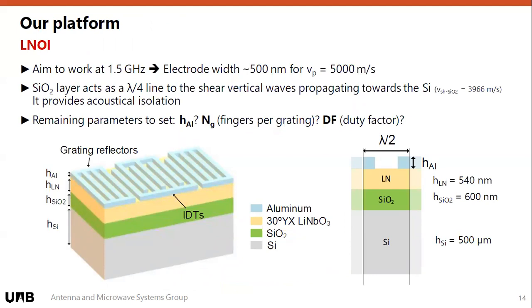So this is our platform and what we have been developing. Initially, we started working at this. Our aim was to work at 1.5 gigahertz just to have something that was manageable, that was lithographically not at the extreme of anything, so that we could focus on the mechanical properties of this. So if we assume, for example, a phase velocity of 5,000 meters per second, that is the ideal value we can get to. So you have an electrode width, because electrodes will be quarter wavelength wide, of around 500 nanometers. This is something that we can define, I won't say easily, but it's not at the extreme of lithography tools.